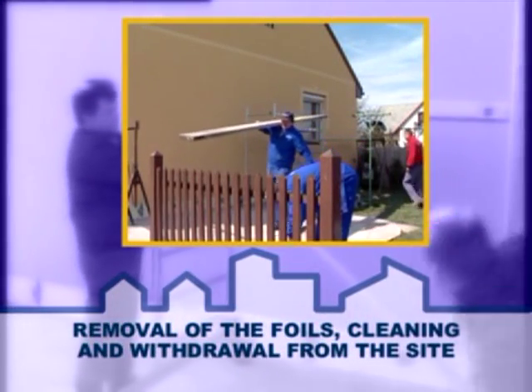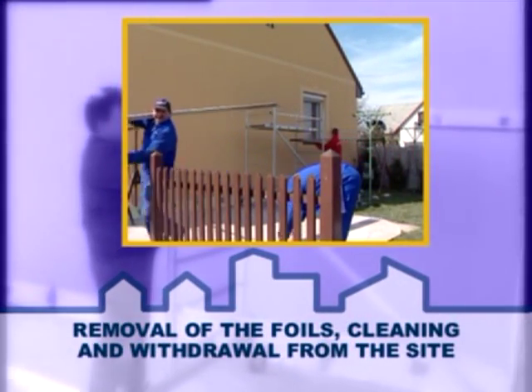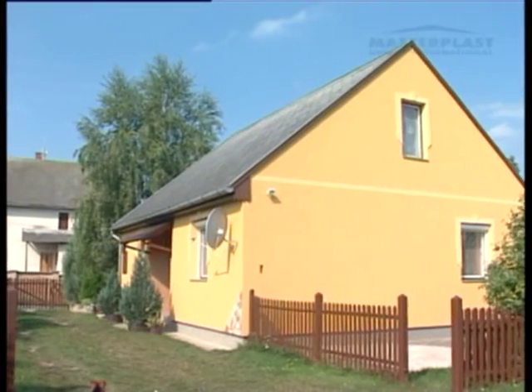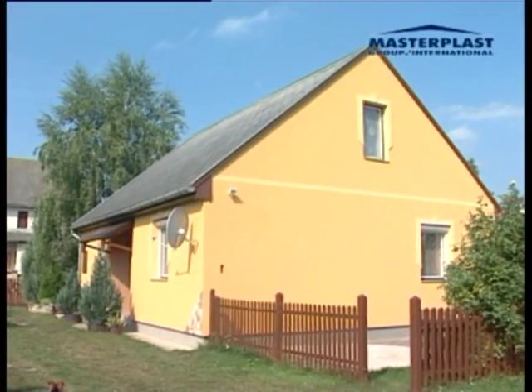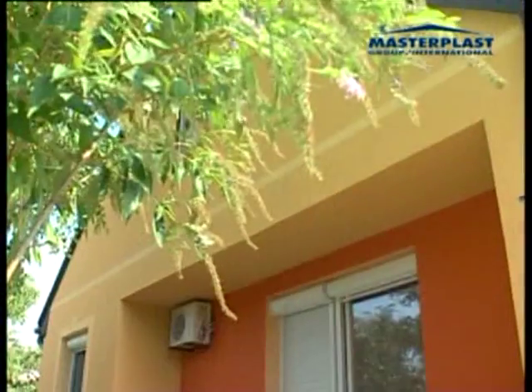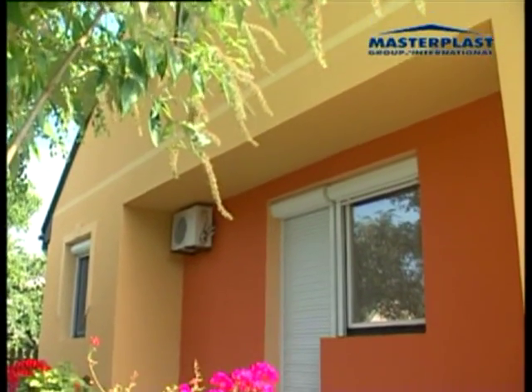The removal of the foils, cleaning and withdrawal from the site. The finished wet render hardens by drying out. The bonding time may be slowed down if the humidity is high or the temperature is low, elongating the process even to 3 or 4 days, whereas warm weather accelerates it. Extreme heat or wind may cause cracks in the render.